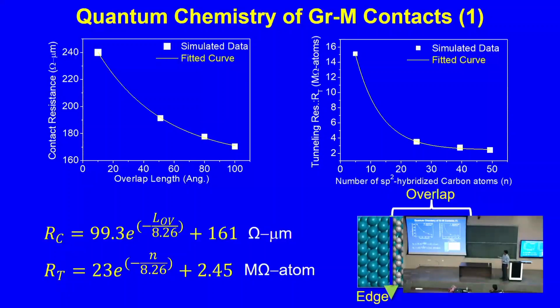So if you plot the resistance versus overlap length, and extrapolate this to 0, it does not go to infinity. If you extrapolate in this direction you get the infinite overlap length, and in this direction the 0 overlap. What you find is that even in case of 0 overlap, there was 40% conduction. So the edge was contributing 40% of current compared to the overlap region.